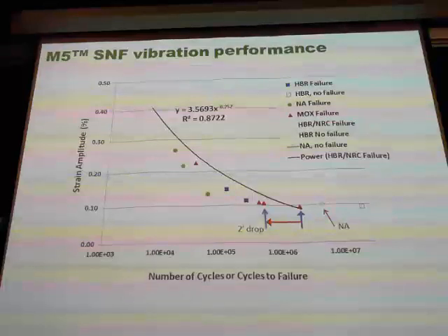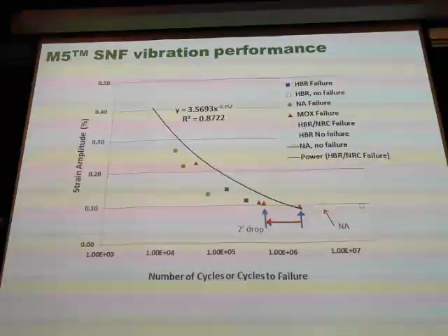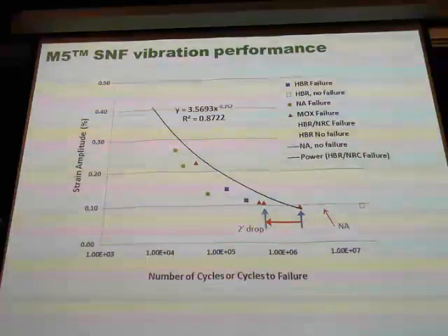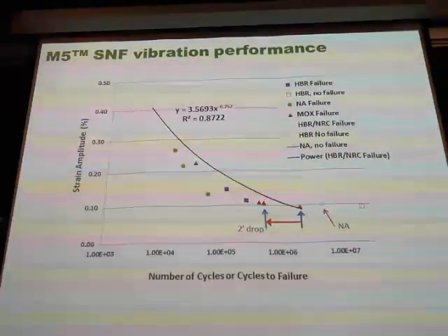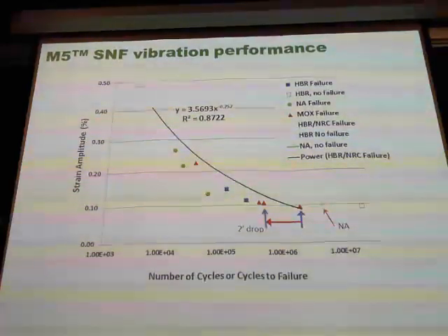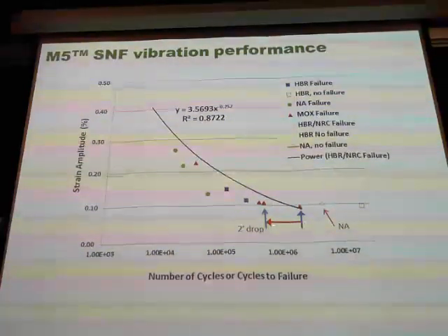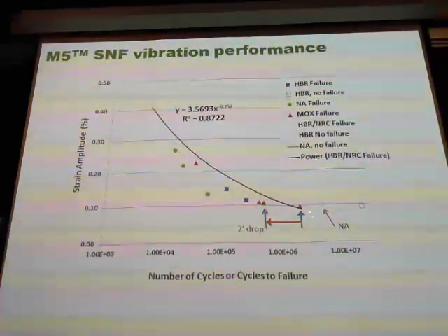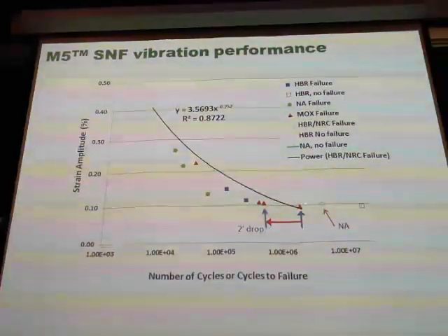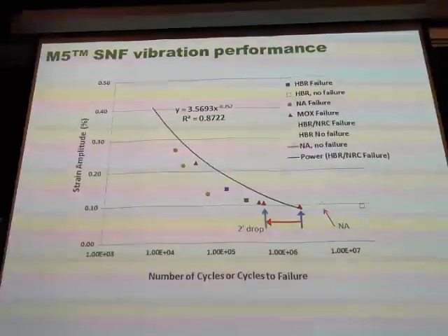And here, this is MOX fuel M5. This one is just an accident. My operator actually dropped one about 2 feet high. Then I said, what the heck, drop one more time. So we dropped it twice. Then we did the test. This is called a tripping shock, accumulated damage, accelerated aging. Under the same loading, there's a slight increase in curvature because of potential damage by the tripping shock. So they come back here.